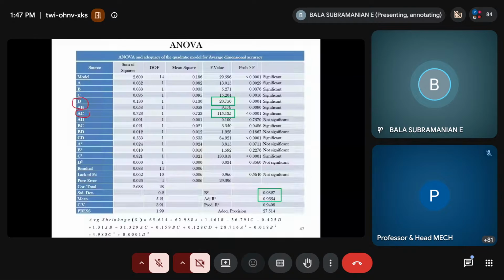Okay. So similarly, we have done it for other aspects like mechanical, tensile, flexural. Okay. So then fuzzy logic, fuzzy rules were formulated. Simulated annealing was used here, and based upon that, we have obtained the results. And for the tensile strength and the flexural strength, what could be the process parameters? And then we have done the wear rate. So this is the RSM and fuzzy logic. So it was like parallel work between different PhD students. I'm just conveying in a very short time.